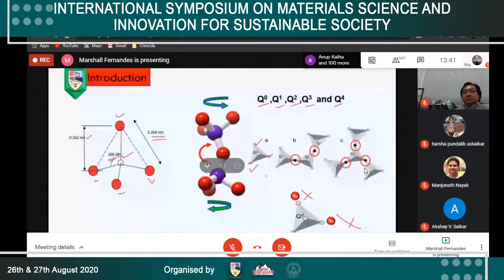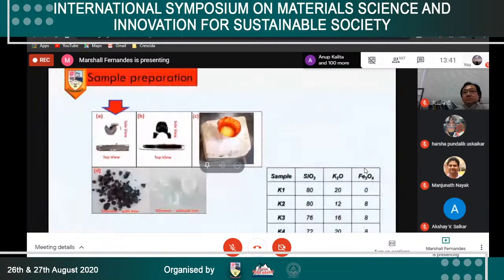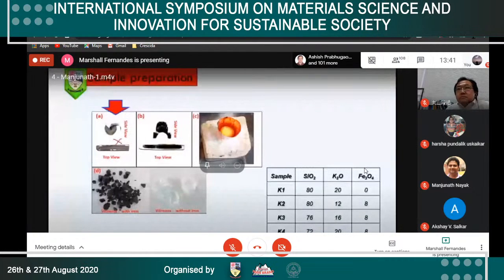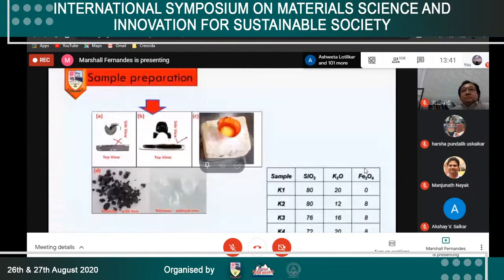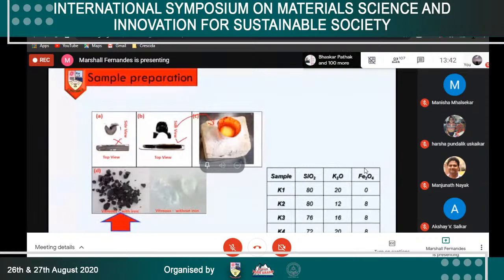All samples were prepared by the method of melt quenching. The one in figure A is a picture of a failed sample due to the choice of wrong composition, and figure B is of the perfect glass sample. These samples were then scaled up to 15 grams in a platinum crucible, heated up to 1450 degrees Celsius, and air quenched within the crucible to obtain the final glass samples. The dark samples are the ones with iron and the transparent are the ones without iron. Here on the right corner are the compositions of the samples presented in this talk.